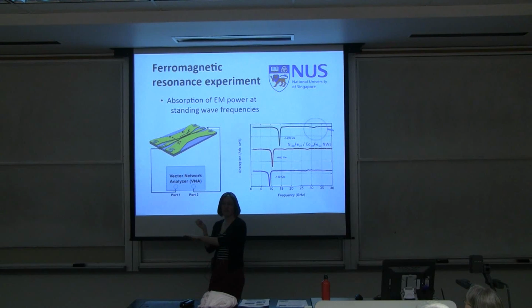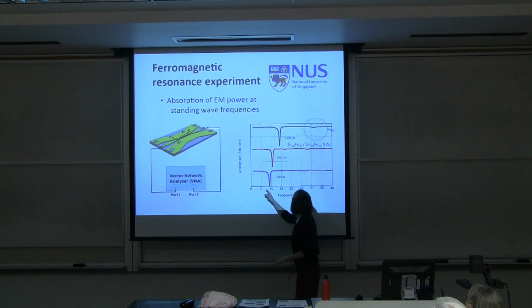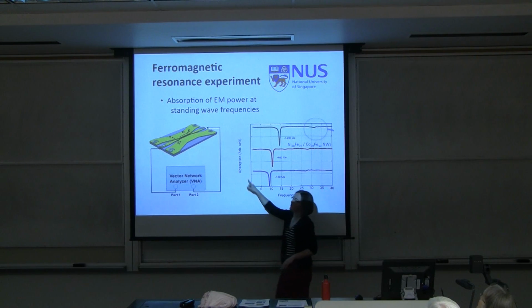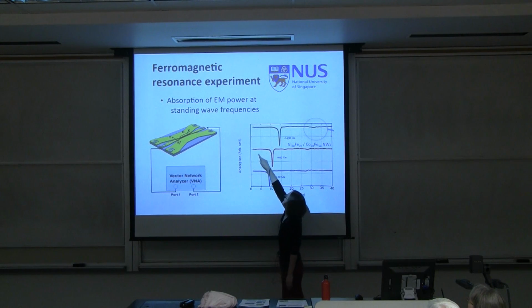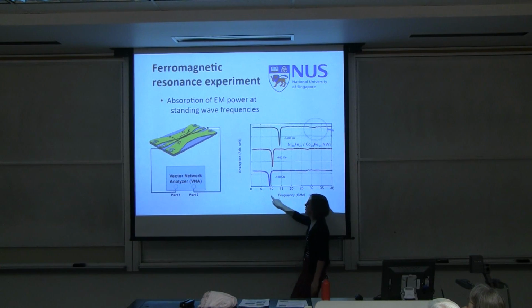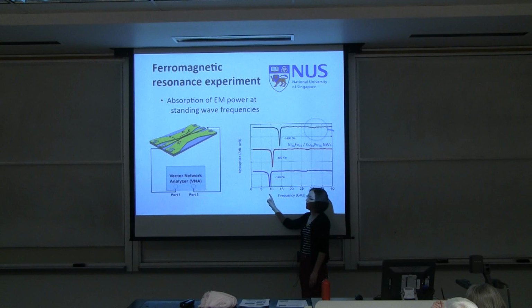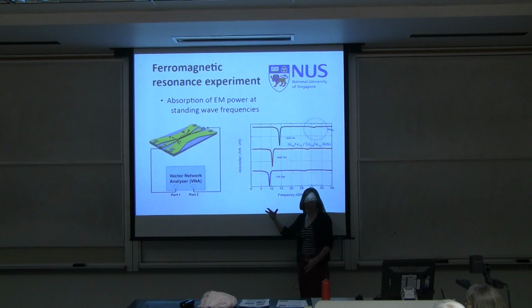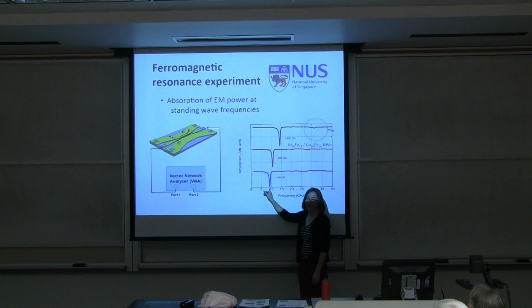And at certain frequencies, the sample absorbs power strongly from that wave that's wiggling it. And when you have that strong absorption, you know you've hit a resonant frequency for the system. Okay? So this is a plot of frequency and the absorption by the sample. And you can see that, say this one, we have a strong dip. So that means that for a field of 140 Oersteds, we have a resonant frequency or a standing spin wave mode at about 9 gigahertz.